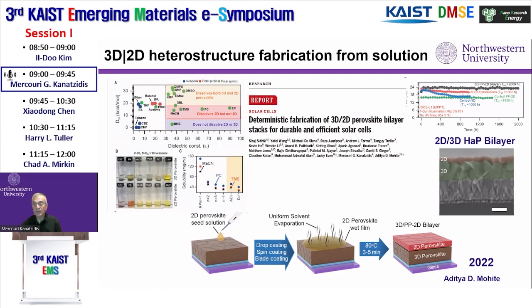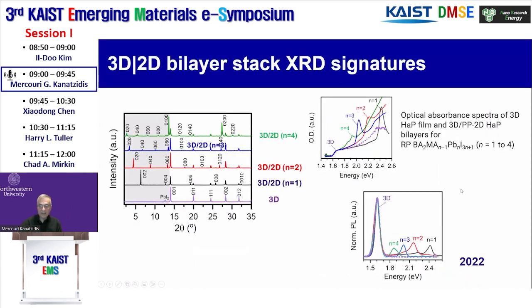devices are quite stable. Here's a stability plot again of a device that has 24% efficiency, which is a 2D on top, 3D on the bottom. It's very stable compared to other devices that have mixtures of 2D and 3D. And so we characterize these things, and we can do different thicknesses and different N values on top of it, and the diffraction patterns are shown here. And we can characterize them.